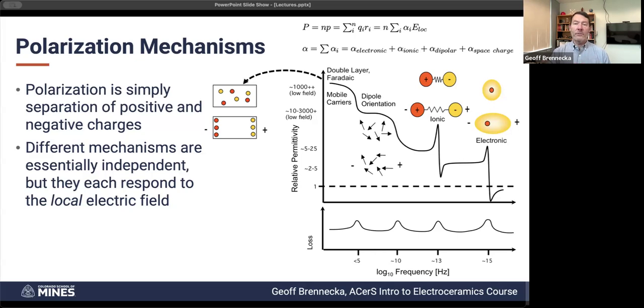So we'll talk a little bit more about relaxor ferroelectrics, where you've got polar nanodomains, where you do actually have flexibility to rotate polarization within unit cells, but that takes a really squishy lattice and sitting right at a phase boundary where things are flexible enough that you can move around. But we'll get into the mechanisms of this dipolar orientation a lot more as we go. One key about this one, though, you'll notice it does not have a resonance. So as we increase frequency, we don't see a resonance for this kind of behavior. And that's because there's no restoring force.